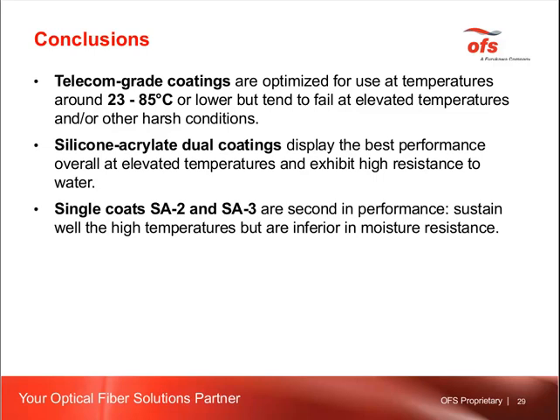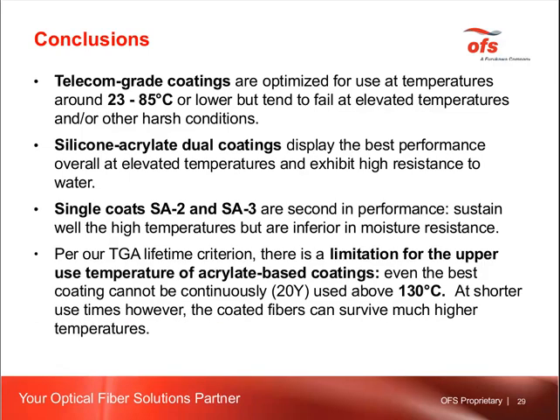They sustain high temperatures well, but they are sensitive to moisture. That is their deficiency. And once again, per our TGA lifetime criterion, there is a limitation for the upper use temperatures of acrylate-based coatings. Even the best coatings cannot be continuously used above 130 degrees C. At shorter use times, however, the coated fibers can survive much higher temperatures.